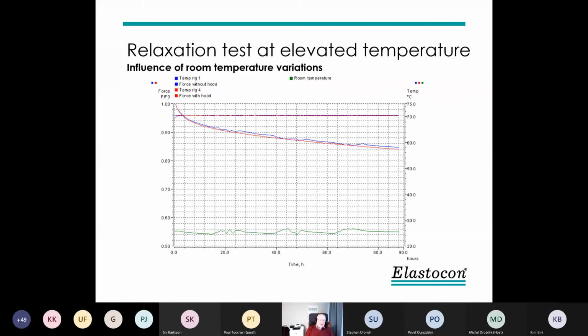Next thing, we have a test rig standing in the cell oven. Then the lower part of the test rig and the sample are kept at constant temperature. But still, we have the upper part exposed, and the load cell is also sensitive to temperature variation. The green here is the same room variation you saw in the graph before. And the blue curve here is the result in the force. It's still influenced by the room temperature. So if we also manage to control the temperature on the upper part of the rigs, we get the red curve. We can get a stable reading.